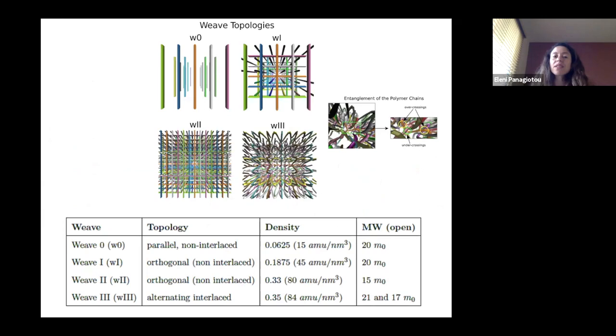We did all that because we wanted to measure linking in systems with periodic boundary conditions, which simulate polymers. Here we did a very toy model simulation of some polymer-like systems. We have this bead spring model where we place the original chains in very specific original conformations. They are not random or equilibrated conformations. They start like this, but that allows us to really control the initial topologies and understand their effect. Also, those systems are very short chains, very well below what is called the entanglement length, the characteristic length beyond which entanglement has mechanical effects.